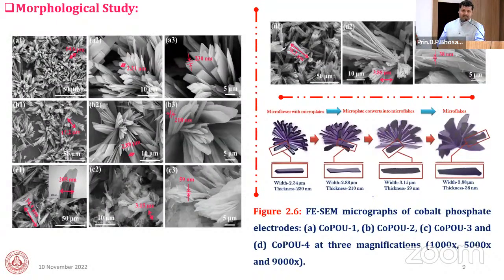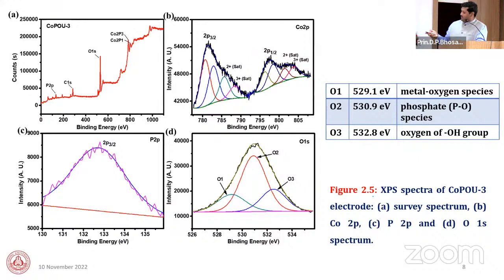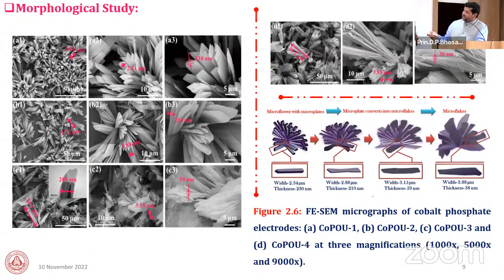Then I studied the morphology of this material at different magnifications, and with increasing urea concentration, the morphology changed a little bit. It means it did not change drastically, just the size, shape, and thickness changed with increasing urea concentration. In the first figure, you can see this is a microflower with microplate-like structure, and with increasing urea concentration, it alters to a microflake-like structure. It means the size and shape is reduced. This is the morphological evolution of microflower to microplates to microflakes.